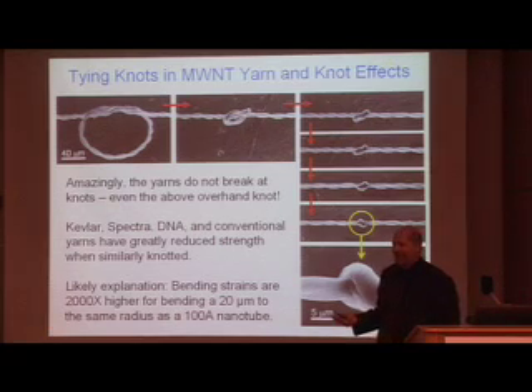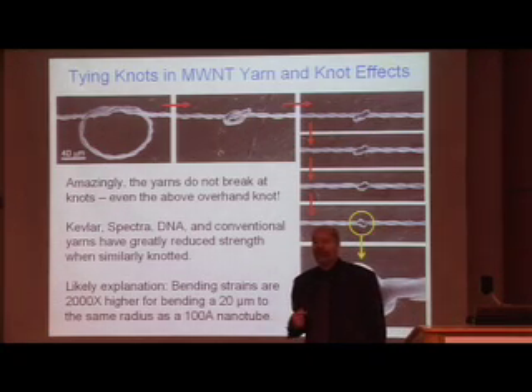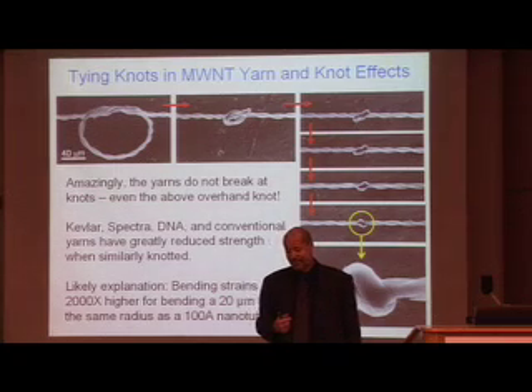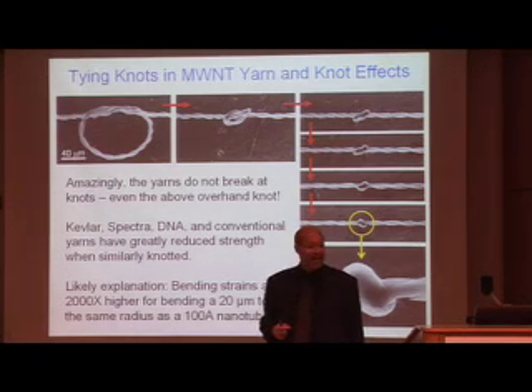What is special about these yarns? Well, if you take any fiber, from the Kevlar and Spectra fibers that are used for anti-ballistic vests, to a wet noodle or a strand of DNA, and you knot it, it will break at the knot. These carbon nanotube yarns do not break at knots. Now, why is this the case? This is an inherent feature which arises because of the nanoscale of our fibers within our yarns.